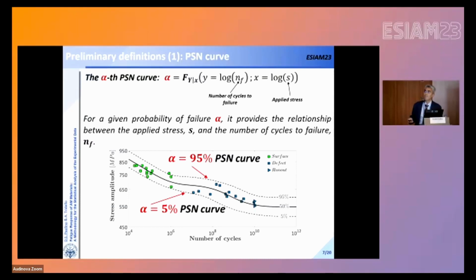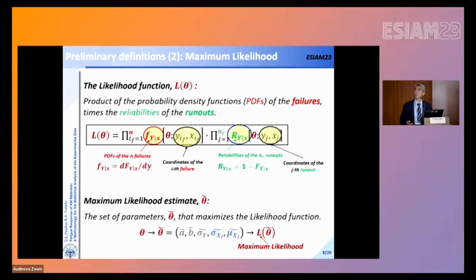Here you can see the 95% probability and the 5% probability SN curve. Obviously, if you want to draw these curves, you have to estimate the parameters involved inside the probabilistic model for the SN trend. We have 5 parameters for the linear with fatigue limit, and 3 parameters for the linear trend without fatigue limit. How can you estimate them?